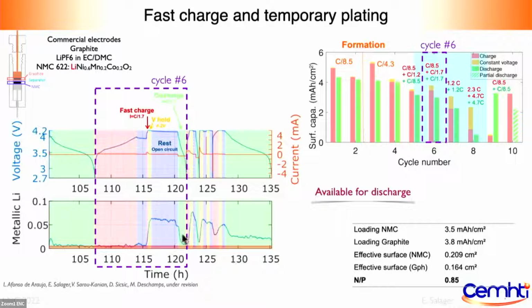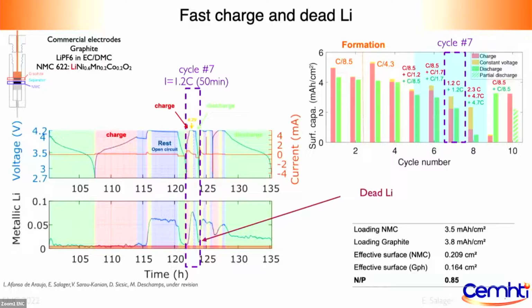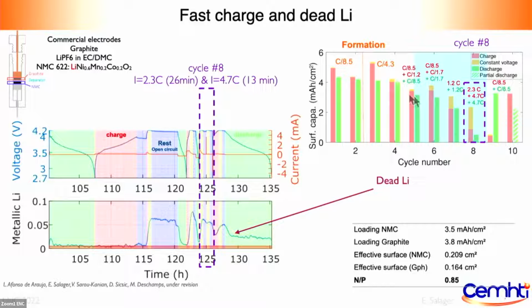In green here, the amount of lithium is retrieved, not all of it, but most of it can be retrieved, and this can be seen by the relatively good capacity that is left. And so what we saw is that if we go faster, charge in 26 minutes or 13 minutes, then we get dead lithium.